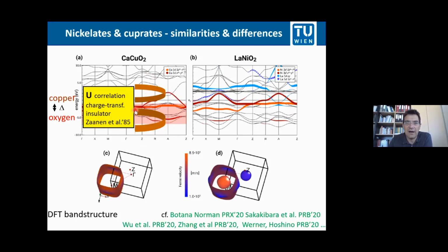So your x squared minus y squared orbital splits into 2 Hubbard bands, and the first holes go now into the oxygen. So in this situation, because of the electronic correlations, the Hubbard model is actually not the proper model for the cuprates. You should rather consider an Emery model.